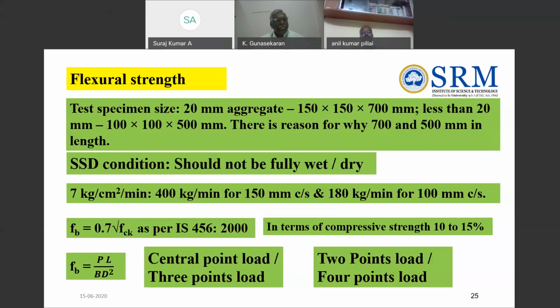And again, here also I am stressing, insisting that it should be in the SSD condition. Like compressive strength, the rate of loading is there; it was 140 kg per centimeter square per minute. Here it is 7 kg per centimeter square per minute. If you are using 150 mm specimens, the rate of loading is 400 kg per minute. And if you are using 100 mm specimens, the rate of loading is 180 kg per minute. Tentatively, if you want to calculate by knowing the compressive strength of your concrete, IS 456-2000 gives the formula to calculate the flexural strength: 0.7 root of fck. But in general, the flexural strength may be in the range of 10 to 15% of the compressive strength of the particular concrete.